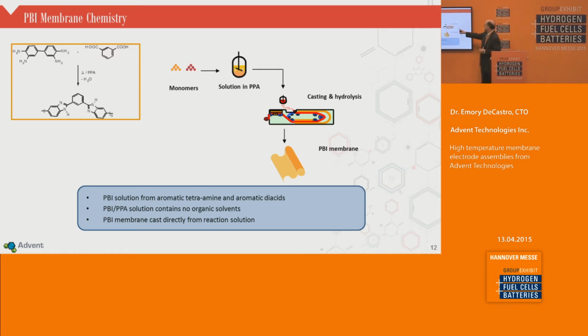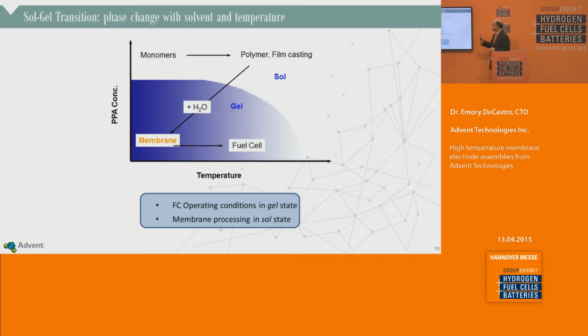You can extrude it. Then when you hydrolyze that, you actually get a phase change, and it goes from a soft, viscous solution to a very plastic-like gel. That's really shown here. So we start with our monomers, form the polymer, form a sol, we hydrolyze that, and now it becomes this plastic membrane. It's actually a phase change, which is good because it allows you to incorporate a very high level of phosphoric acid in a uniform manner, but it also defines the operating limit for this platform because you cannot go too hot. You'll start to shift it to the sol phase, and you can also not dehydrate it so much that you shift to polyphosphoric acid.